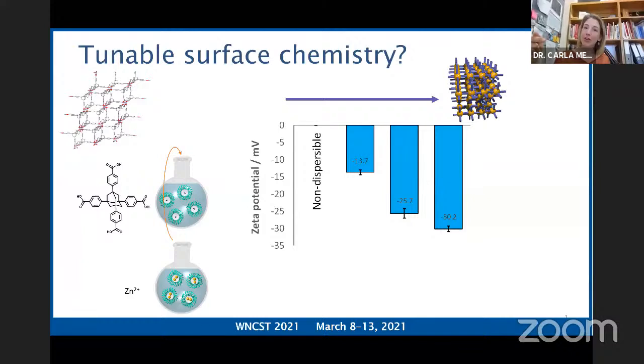So now we want to try and go in the other direction, and can we intentionally create the crystals so that they have a high density of metal ions at the surface? And you can imagine what that allows us to do. If they predominantly terminate with the ligand, then we can use these carboxylic acid groups perhaps to start incorporating these nanocrystals into gels or other polymer type matrices to form hybrid materials.